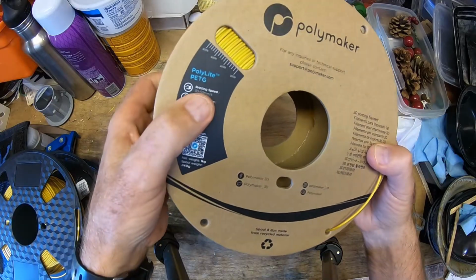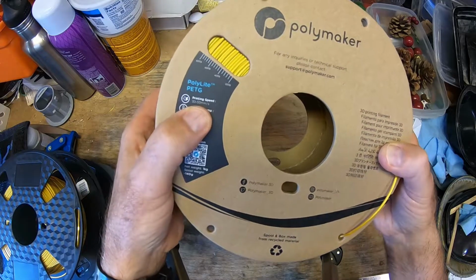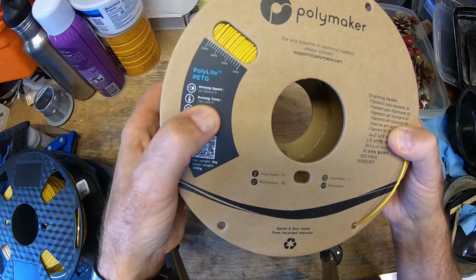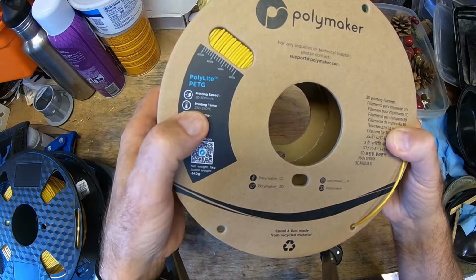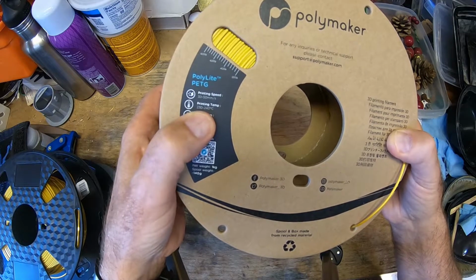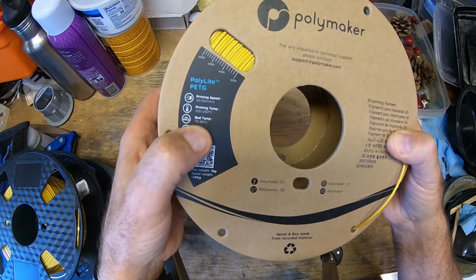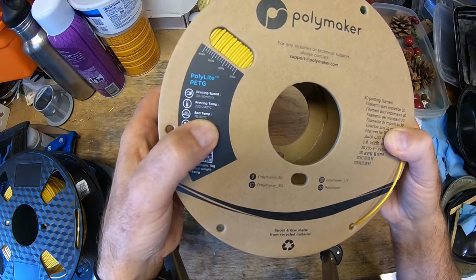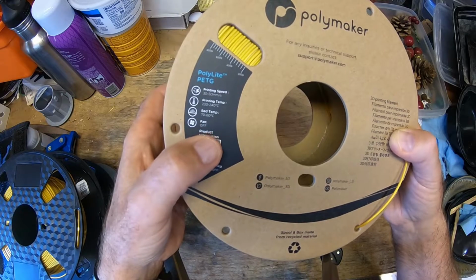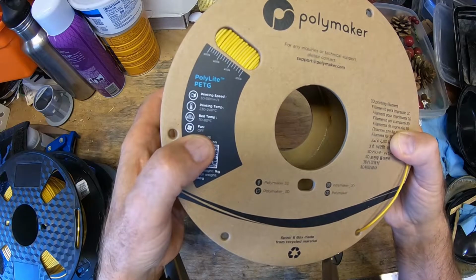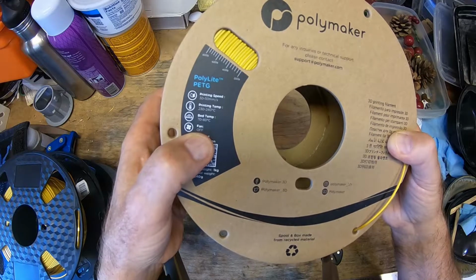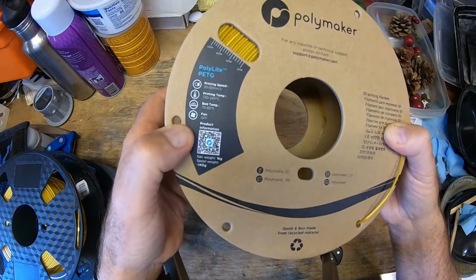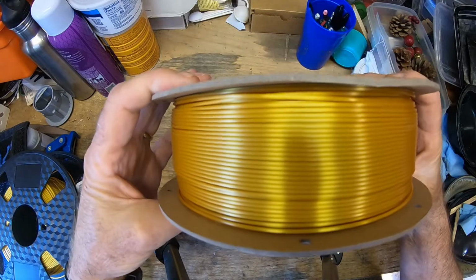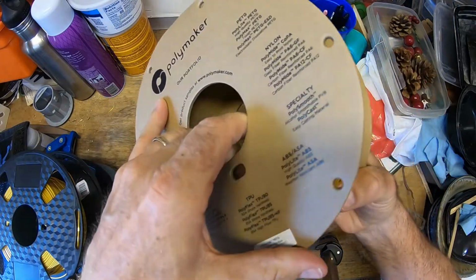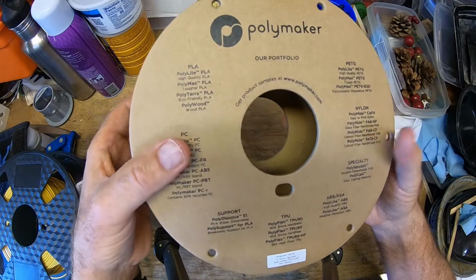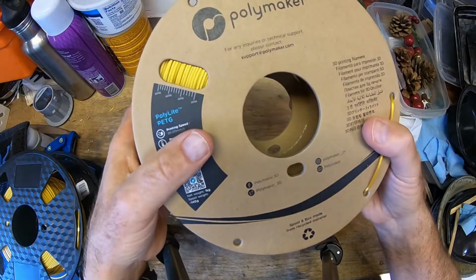So let's see, it says printing speed 30 to 50 millimeters per second, printing temperature 230 to 240, so that's good. We like to print at 237, and bed temperature is 70 to 80, so now I've usually been using 65, so hopefully that'll work. It says fan off, but I've been using fan on the second layer at 10%. I get better results with that. So I'm going to try to print this. We'll do the temperature tower and do the other things, but hopefully we can print it the same way we're printing the rest of our PETG.